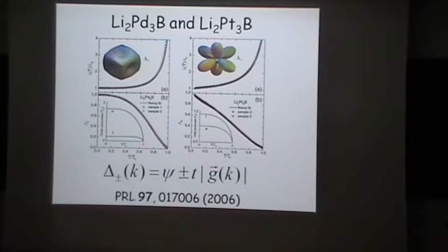So in principle, you can look for two Fermi surface sheets using the de Haas–van Alphen experiments. And I think in the context of some of the heavy fermions, Onuki has done this, and he has seen spin-orbit gaps. They are typically a fraction of the Fermi energy. They're not comparable to the Fermi energy.